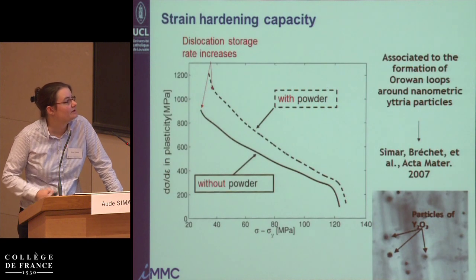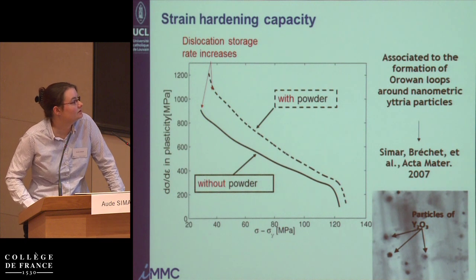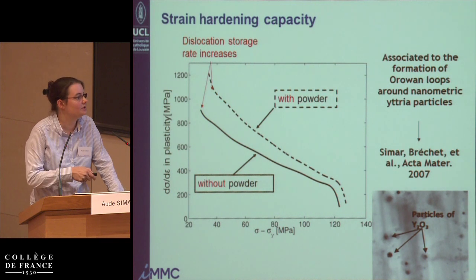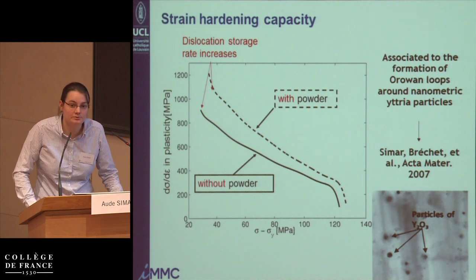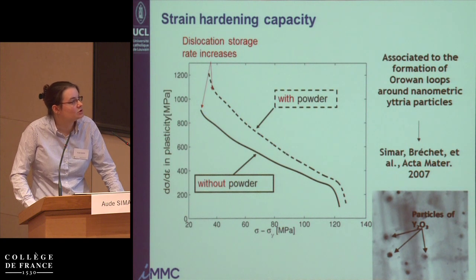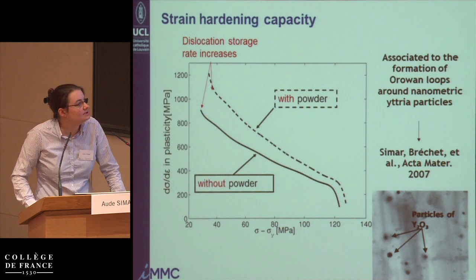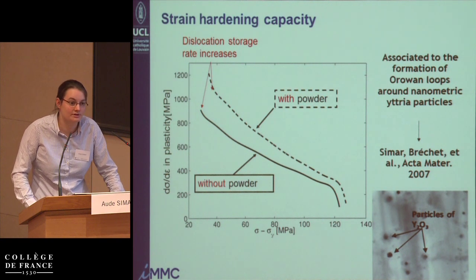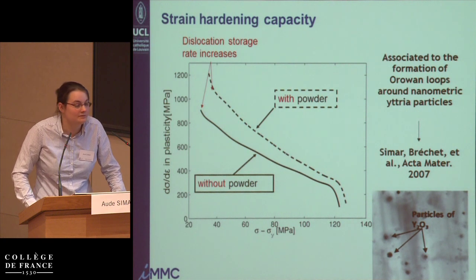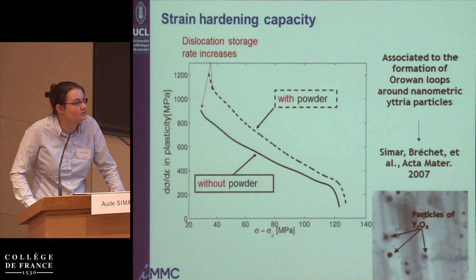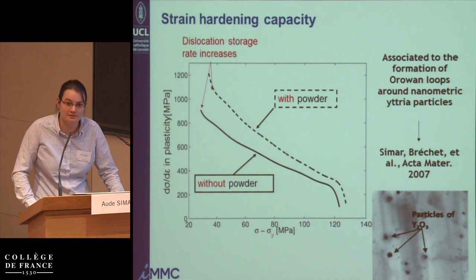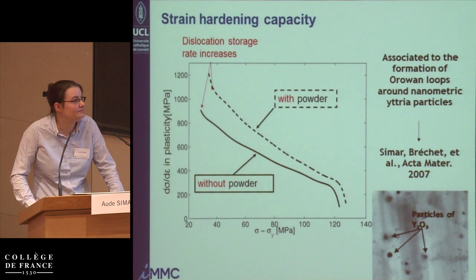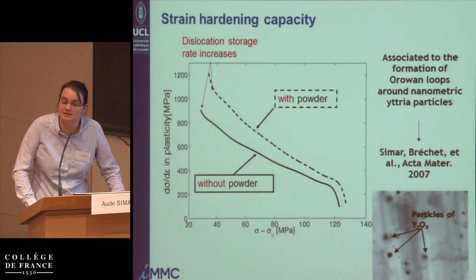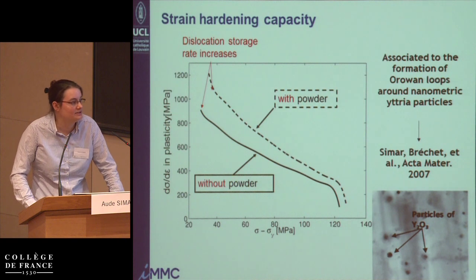And when you look at the evolution of the plastic slope as a function of the stress, so this is a Kocks plot showing the evolution of the strain hardening ability, you see that these materials have a better strain hardening ability than without the oxide powders. And so with Yves Bréchet, we've done some work in the past in aluminum alloys, looking at the effect that these nano precipitates could have on the strain hardening ability. And here we find that indeed the presence of nanoparticles in the material improved the strain hardening ability.